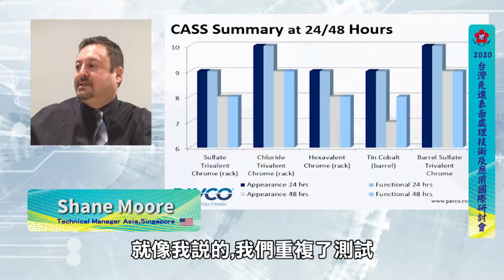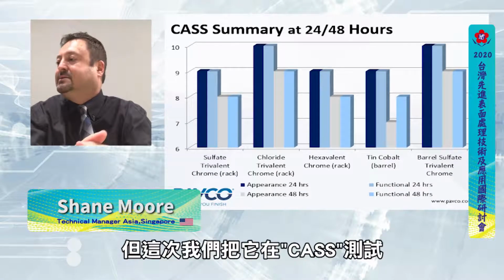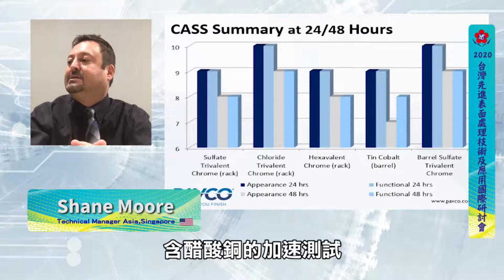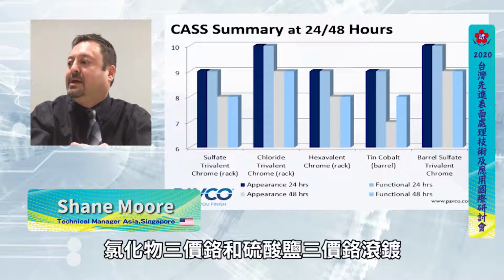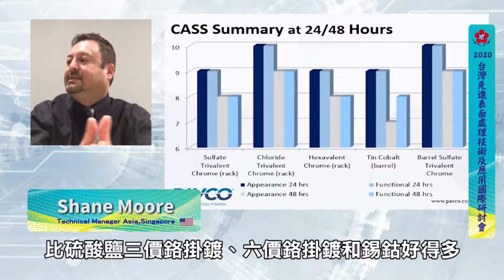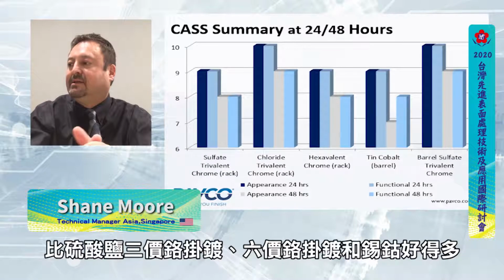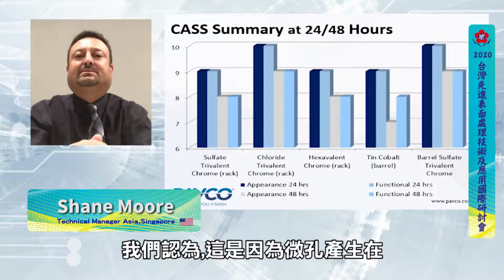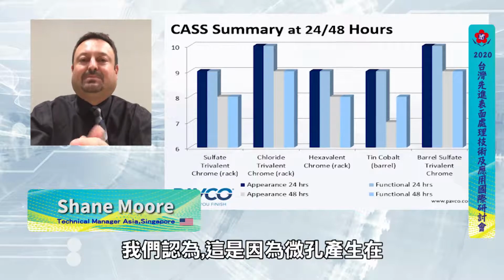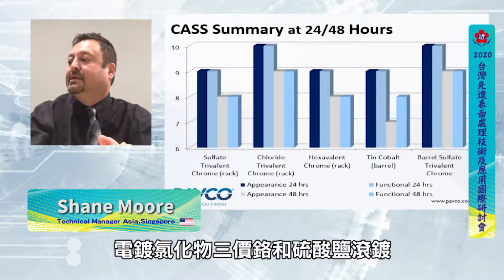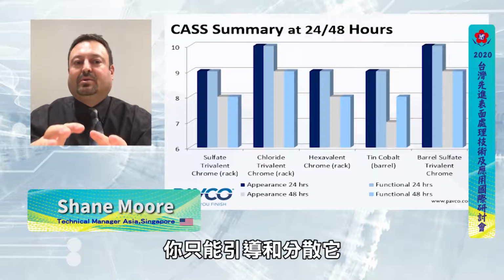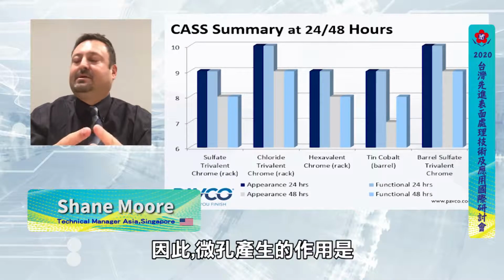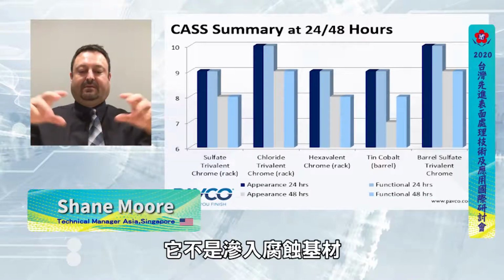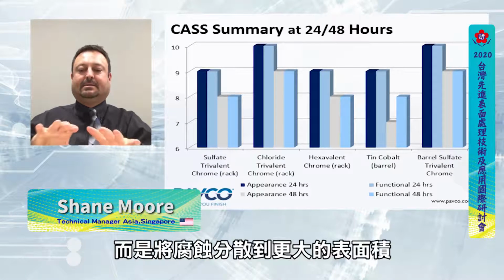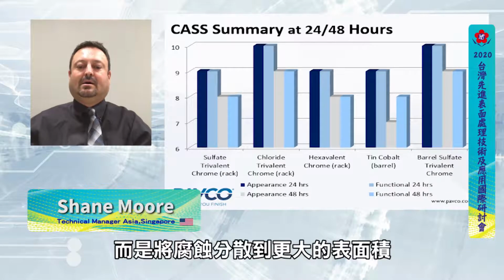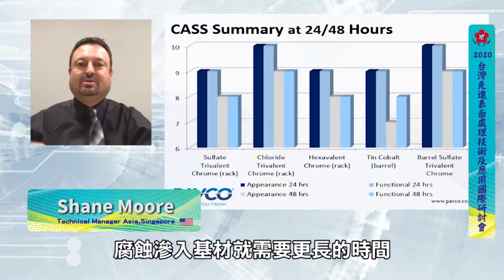Okay, and then like I said, we repeated the test, but this time we put it in a CASS. It's a copper acetic acid accelerated test, similar to salt spray, but a little more aggressive. Chloride trivalent chromium and the barrel sulfate trivalent chromium actually did much better than the sulfate trivalent rack, hexavalent rack, and the tin cobalt, of course. I think that's because the deposit is actually microporous as plated in the chloride trivalent chromium and in the barrel sulfate. So you can't stop corrosion, you can only guide it and direct it. So what the microporous deposit does is instead of it going straight down to the substrate, it disperses the corrosion over many different sites. So that way it spreads it out and it takes much longer for the corrosion to get all the way down to the substrate.